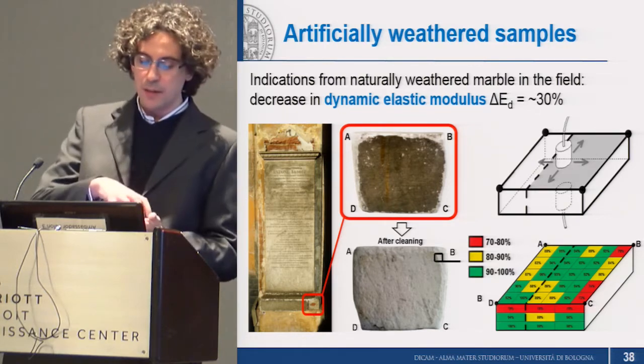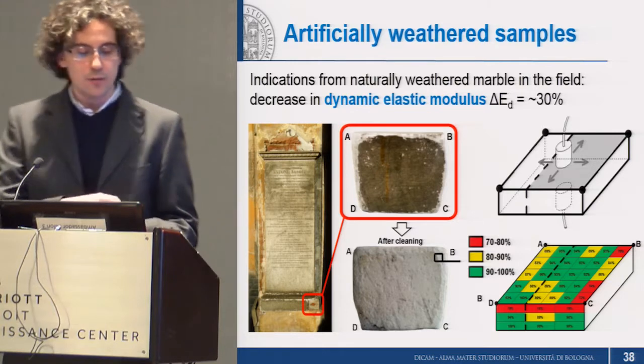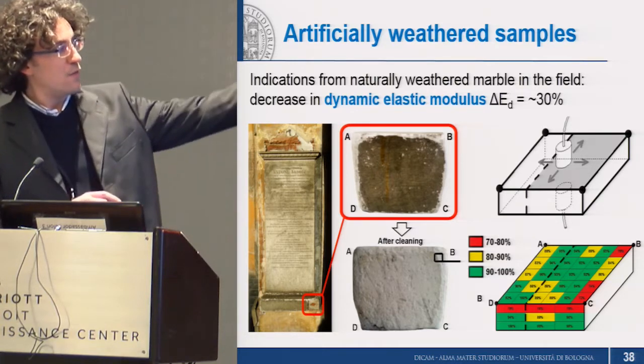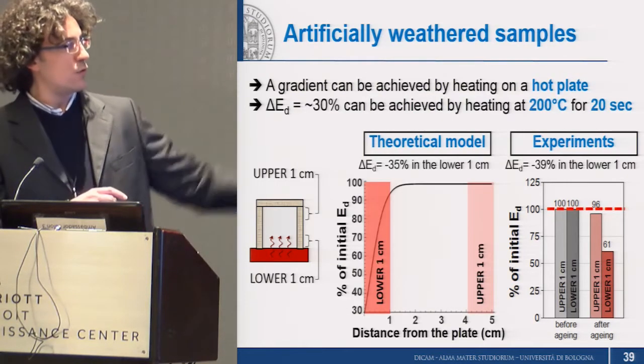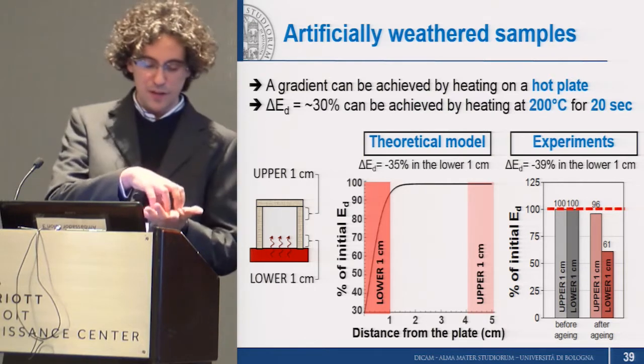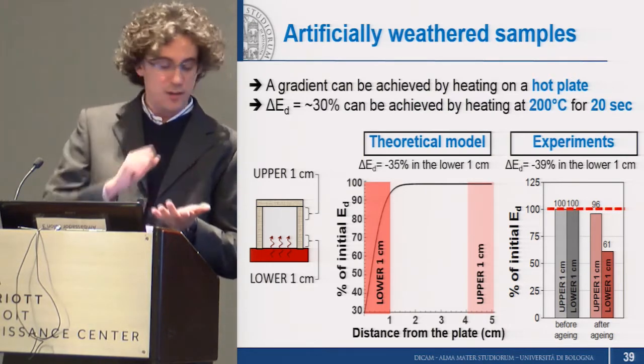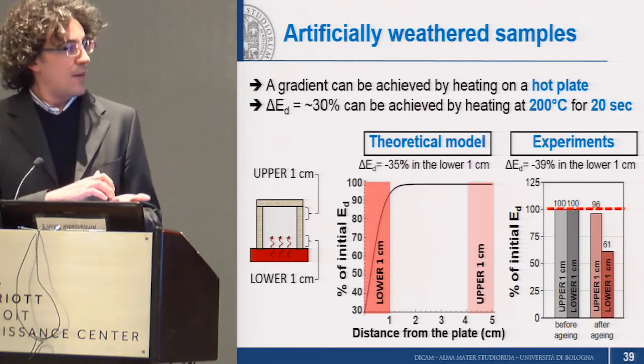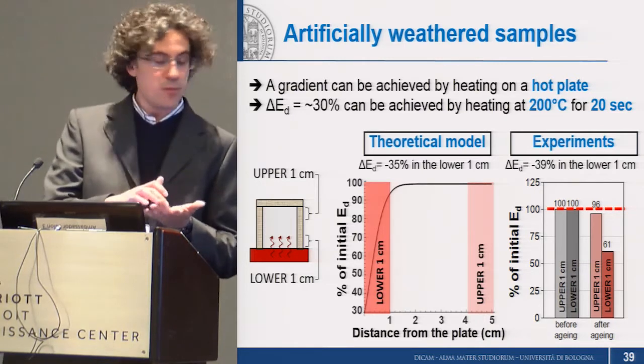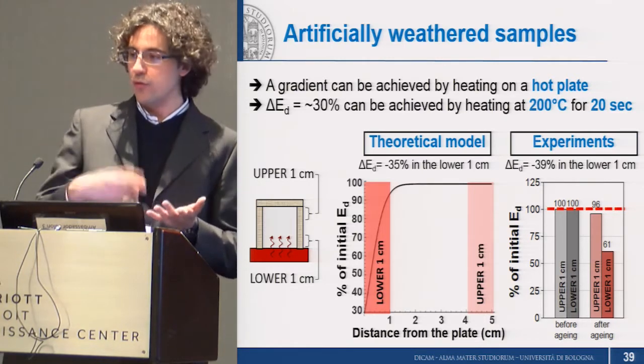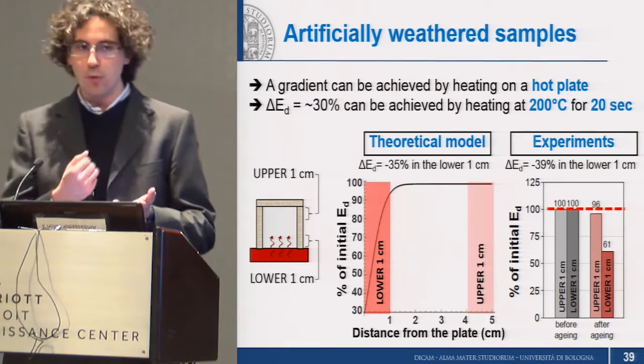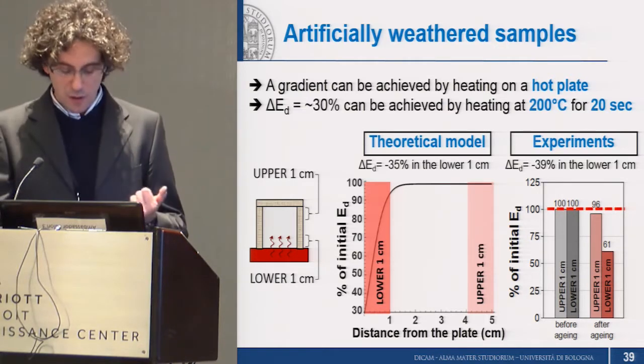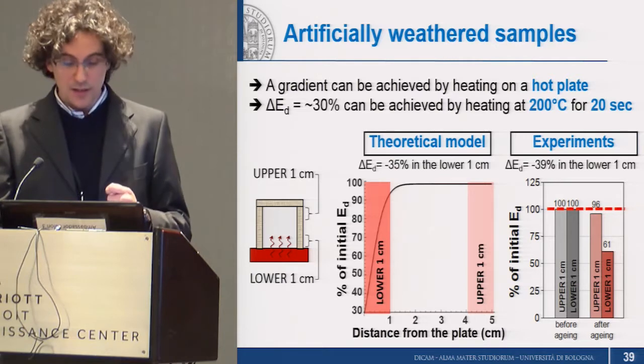So then we developed a mathematical model that allows us to predict, starting from the situation that you can see on the left, a piece of marble placed on top of a hot plate, for how long and at what temperature we should heat it to reach a certain level of damage that we want to achieve, the same level of damage that we found in the field.